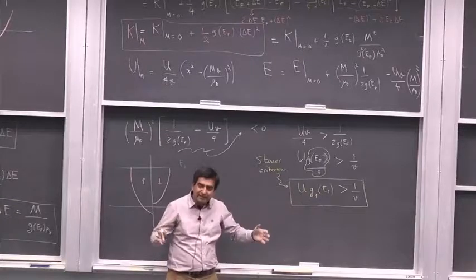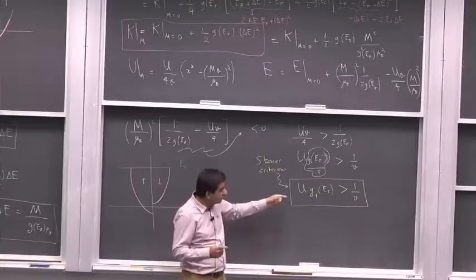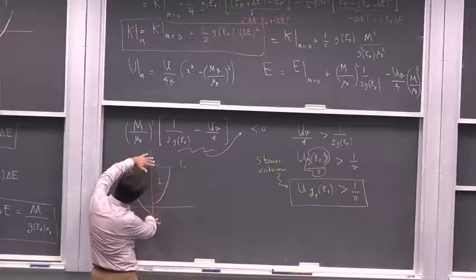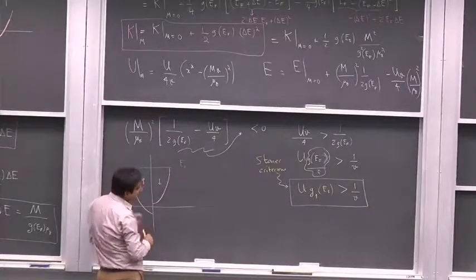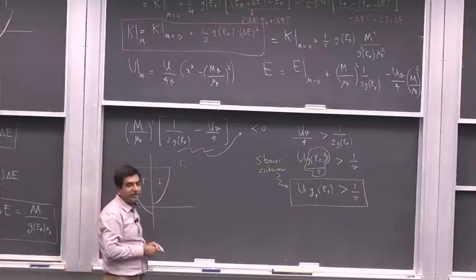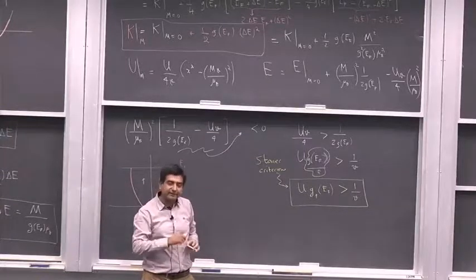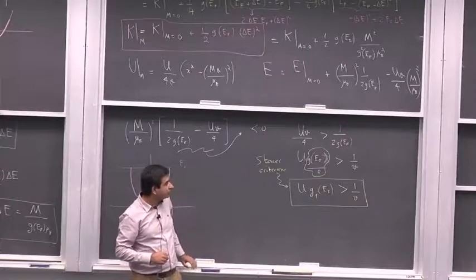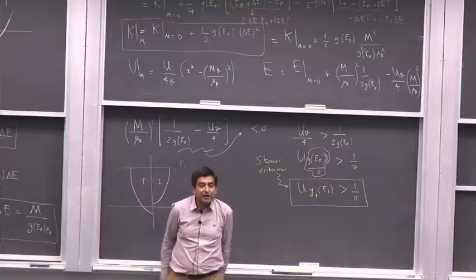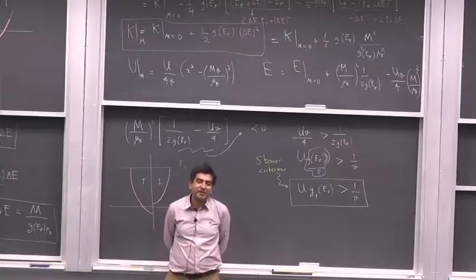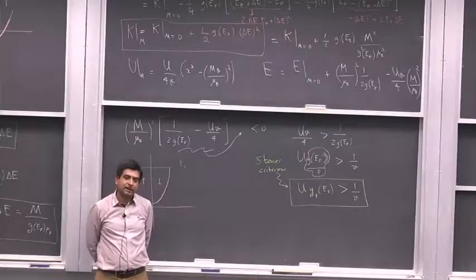Okay? So the collective electrons, the itinerant electrons, when they are correlated, can, if this condition is satisfied, cause the material to spontaneously magnetize itself. And such a material is a ferromagnet. And the three materials, iron, cobalt, and nickel, in the 3D series, obey this property. And that's why they are ferromagnetic. So if this condition is not satisfied, then the sample is not ferromagnetic. However, the susceptibility might be different from the Pauli paramagnetic value. That's possible.